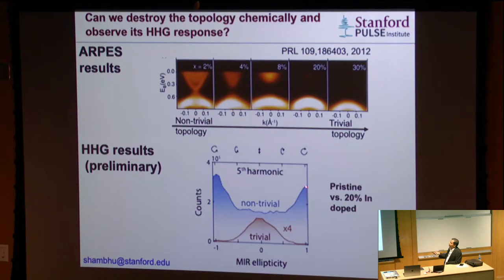Where the signal is maximum for the circular polarization, and this is the data for the 20% impurities. First thing is the efficiency is generally very weak, 4 times weaker. The second thing is that the enhancement for circular field is completely gone.